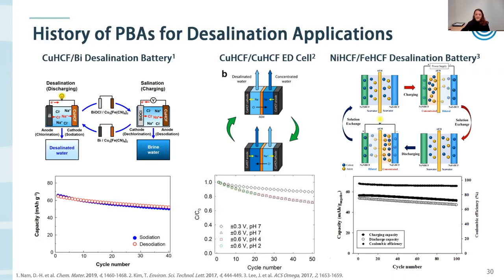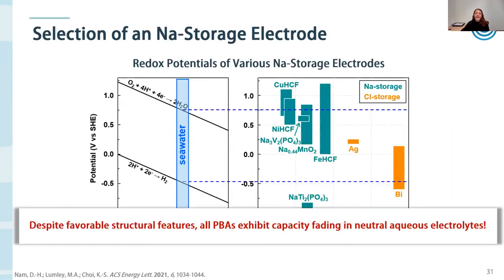But when I was doing my PhD at UW-Madison, we decided to try to investigate why this was happening and see if we could find a way to make a stable Prussian blue analog that could be used for seawater desalination. And so we went back to the drawing board and we decided to choose nickel hexacyanoferrate as our electrode material because it shows the least overlap with the water oxidation potential, which is this dashed blue curve here.